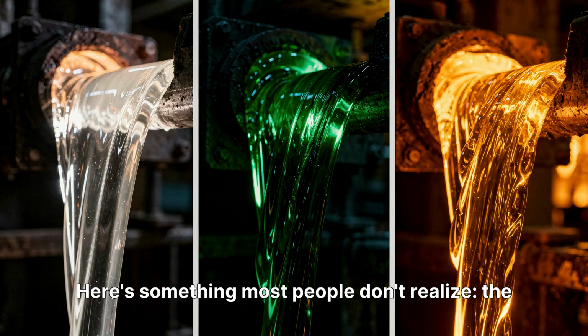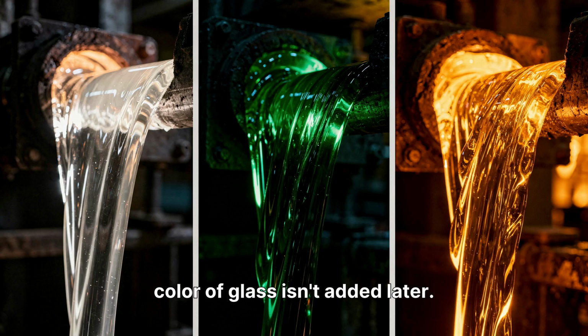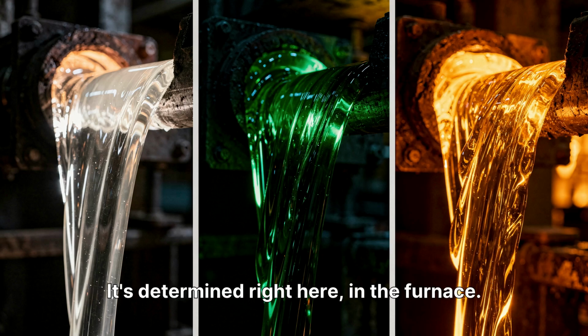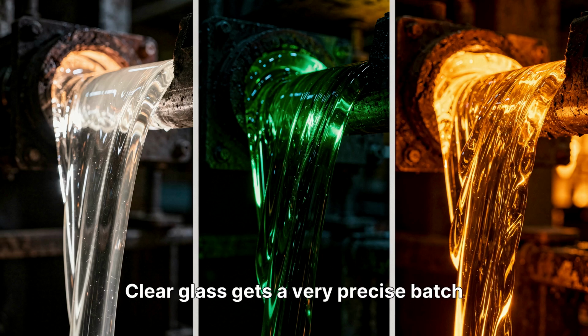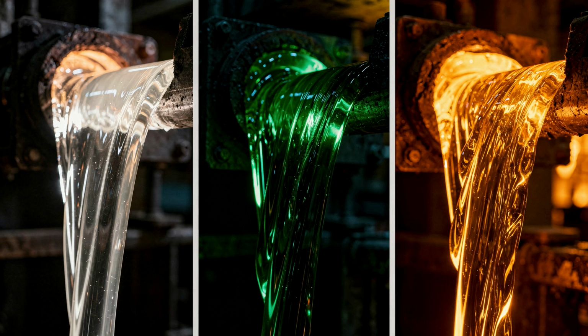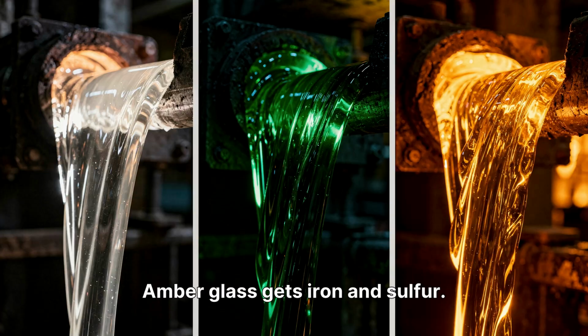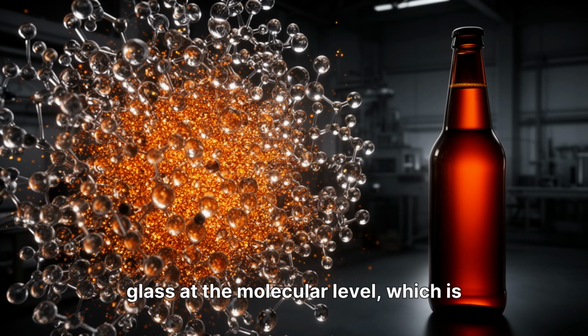Here's something most people don't realize. The color of glass isn't added later. It's determined right here in the furnace. Clear glass gets a very precise batch with no added colorants. Green glass gets iron and chromium. Amber glass gets iron and sulfur. The color is baked right into the glass at the molecular level, which is why you can't scratch it off or paint over it with anything that lasts.